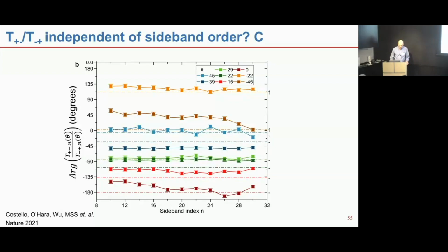And here are all the angles. And so they're all pretty constant. They're not far from the predictions, but they don't agree certainly perfectly with the Luttinger model. And by averaging these, we can get a ratio which has somewhat large error bars.